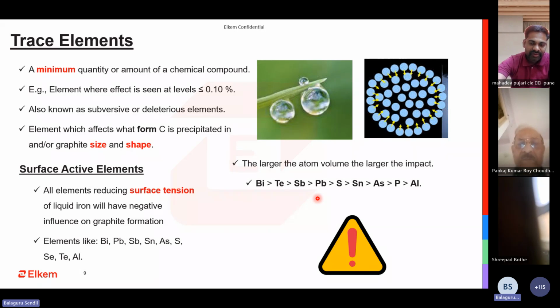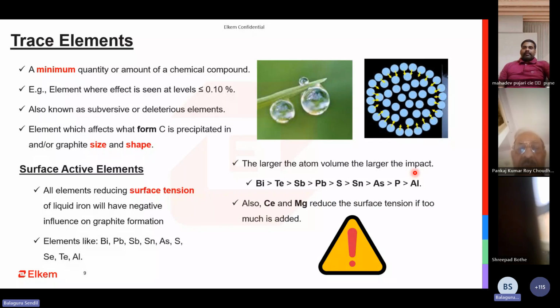The point here is that when you are having a large atomic number, large atomic weight, large atomic volume, the impact it can do to damage the surface tension is high, even when you have extremely low levels. So bismuth at 0.0005 does much more, either good or bad, than aluminum at 0.1. So even at ppm level, this can be much more either useful or dangerous than this one. This is the key takeaway here.